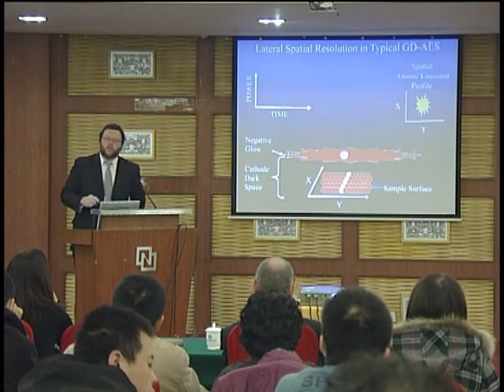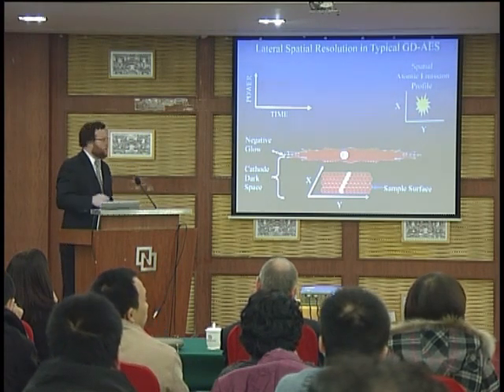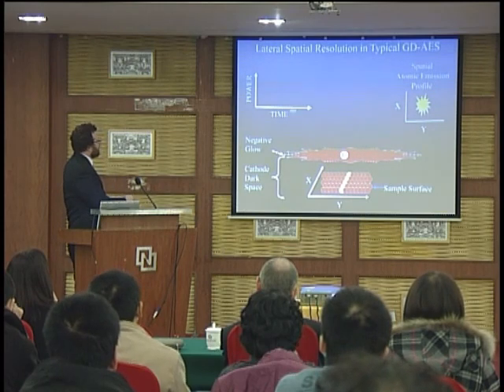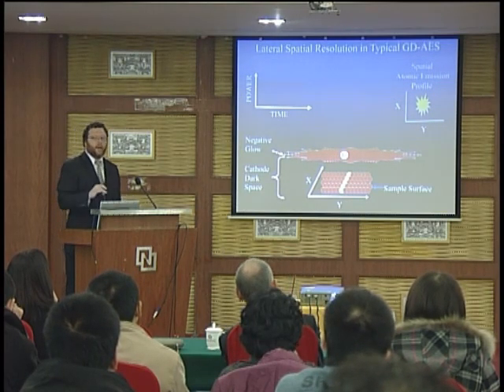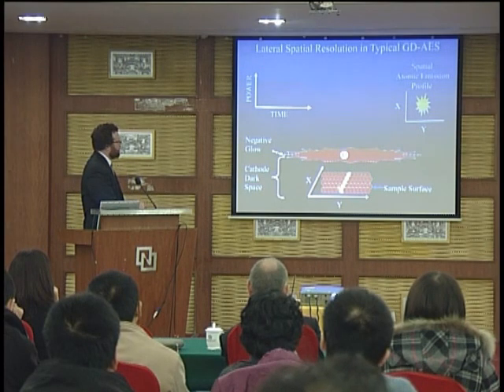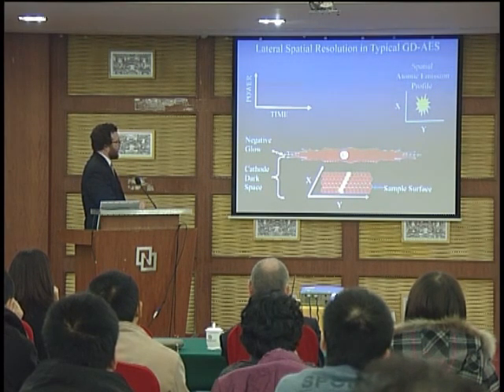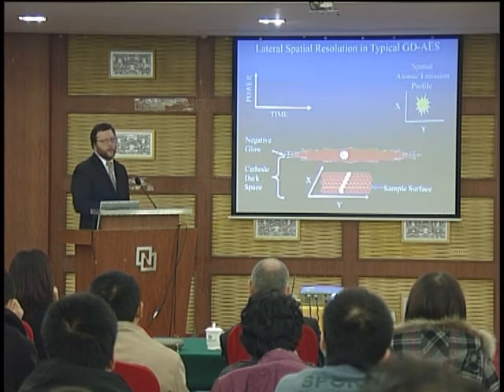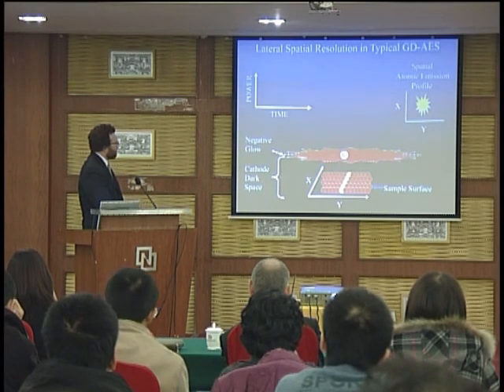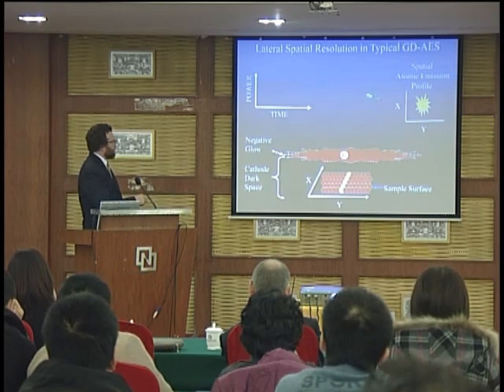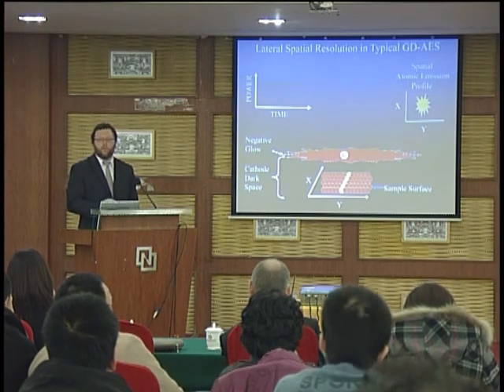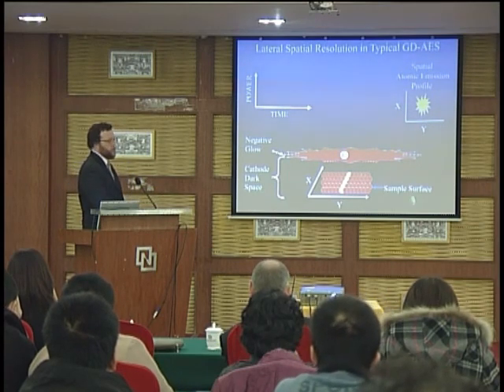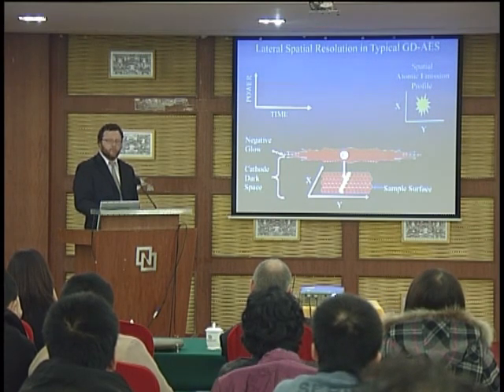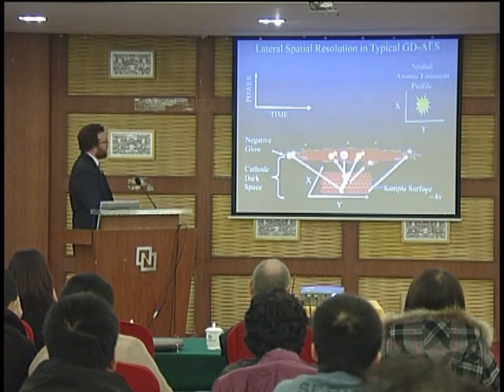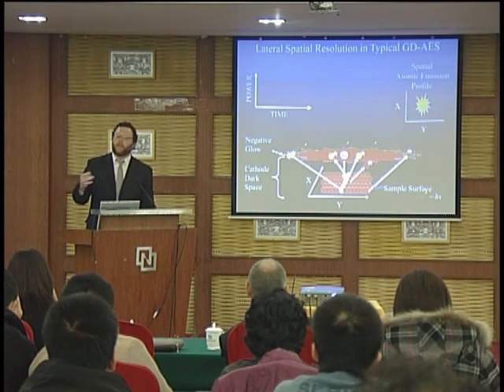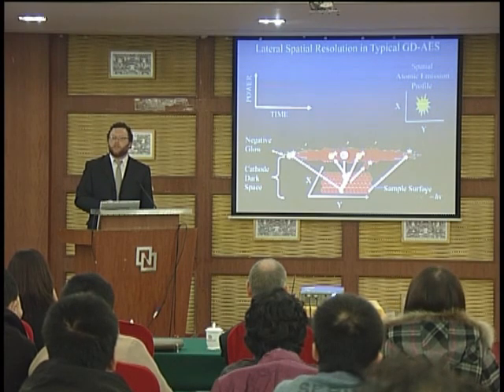Here we go. Okay, so in a typical glow discharge, it's operated continuously, of course, sampled by sputtering. So the power is applied continuously as a function of time. Let's say we had a solid surface that maybe had some morphology to it. Here are a bunch of yellow-colored atoms that are on a base of red-colored atoms. And of course, continuously what's happening is the glow discharge is struck between the anode, which is the vacuum chamber, and of course this is at about a torr of an argon environment, and the cathode, which is your sample. And so sputtering then is going to remove material from the sample surface, and it's going to be sputtered out into the negative glow of the glow discharge, where it'll be excited, and then we'll detect it by atomic emission spectroscopy.